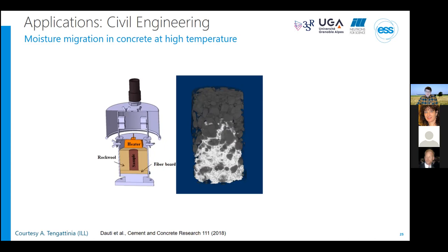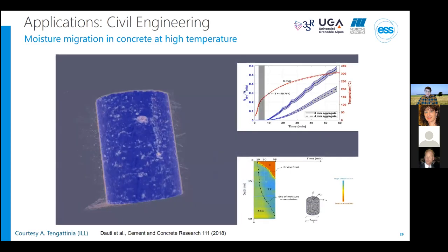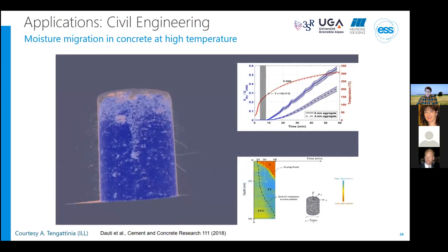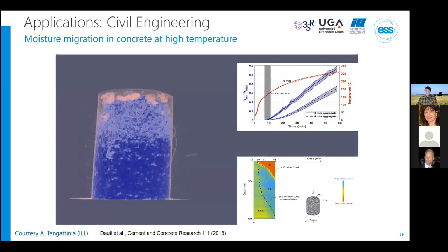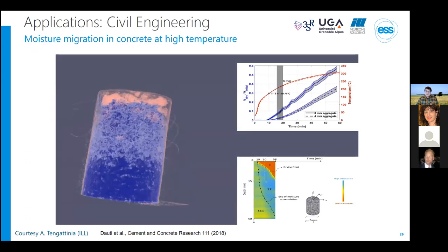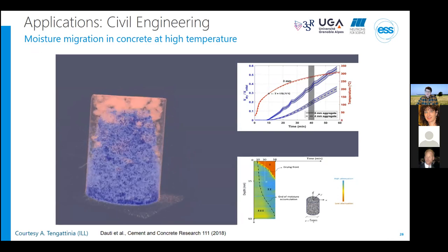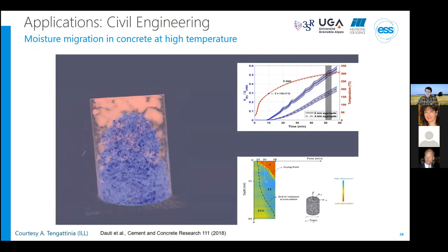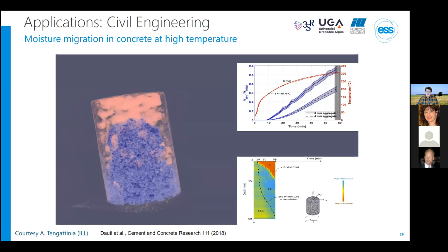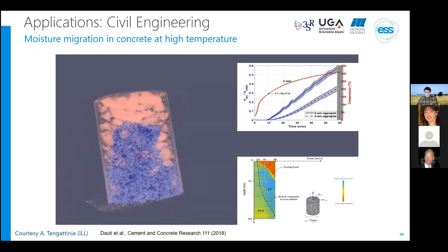And in order to study this, they heated concrete to about 500 degrees Celsius inside the sample environment that you can see here, and then collected a series of tomographies in operando during the process, each one taking about 1 minute. And here we can see now the water front and how it dries, allowing to monitor the speed of this drying front. And then they did this for different types of concrete. And what this graph on the top right shows is that the temperature profile is identical between different types of concrete, but that the drying profile is actually quite different.